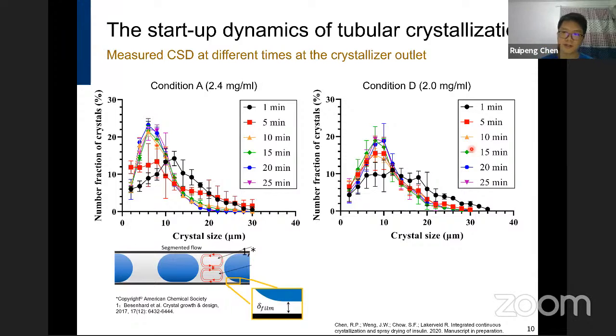Oh, okay, so here it is actually not about the residence time. It's related, but the reason is not directly related to the residence time. We guess the reason for the shift in the CSD is that some small particles can travel between slugs, and these particles have a larger residence time and are able to travel to the other slugs. Therefore, it takes some time for the system to reach the approximate steady state in terms of CSD. And also some particles, as a consequence, will have a longer residence time due to the traveling between the slugs. Okay.